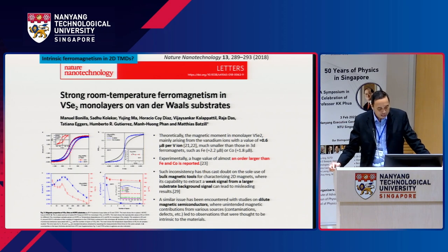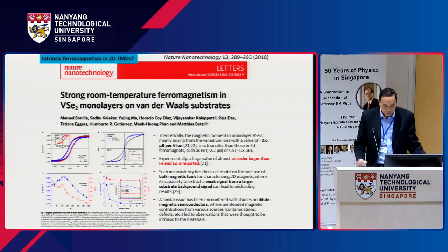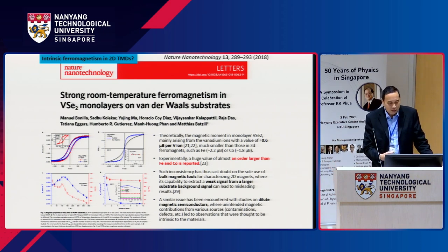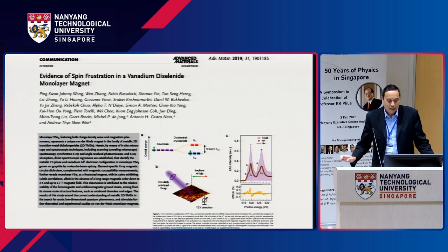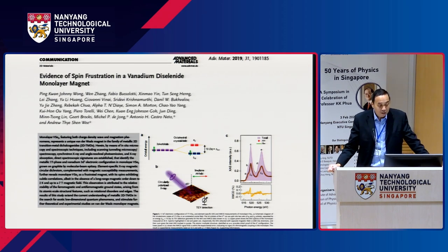So we suspect this could have been the case, and such an issue has been encountered on the issue of dilute magnetic semiconductors. Our interest in vanadium diselenide came about because one of my postdocs, Johnny, happened to be working on this material at the same time, and this paper made him hold back his own paper. He published it in the end a year later, which showed that there was evidence of spin frustration. That means it was not magnetic, but on the verge of being magnetic.